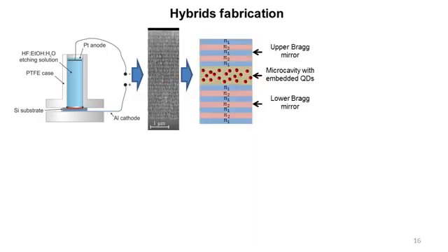In this study we have fabricated two samples, a distributed Bragg reflector and a microcavity. The simple reflector was formed by stacking 25 pairs of layers with high porosity of 75% and low porosity of 58%. Porous silicon microcavities were formed by stacking the front and rear mirrors and the half-wave cavity layer which was placed between them. The front and rear mirrors included 5 and 20 pairs of layers, respectively.